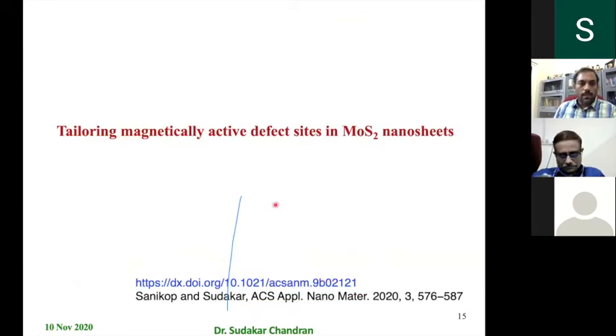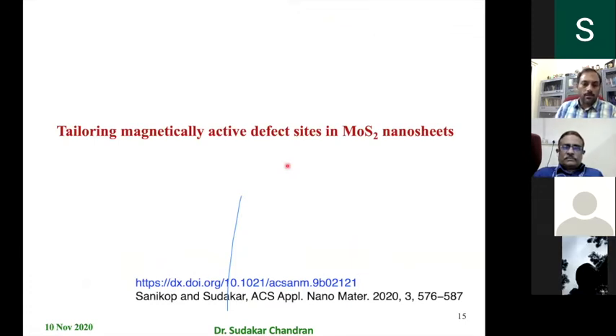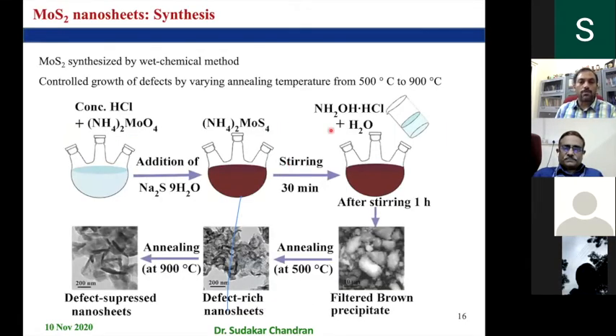Okay, so now with that introduction, I will get on and show how one can tailor the magnetic properties by activating defect sites in MoS2 nanosheets, magnetically activating the sites in MoS2. Remember, MoS2 is diamagnetic because of the trigonal prismatic coordination, where the crystal field is such that the lowest energy level occupies two electrons, and they pair up, therefore the net magnetic moment is 0.